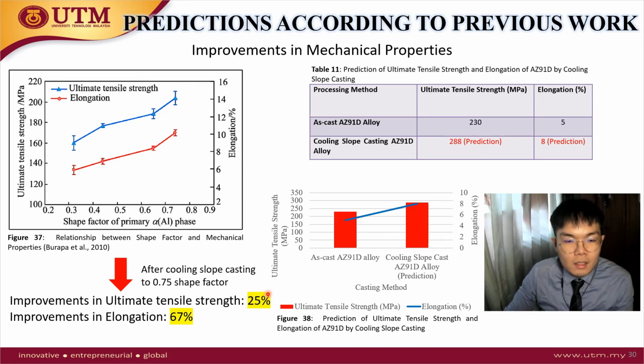By applying these improvements, we predict when we cooling slope cast AZ91D magnesium alloy to become 0.75 shape factor, we can obtain 288 megapascal of ultimate tensile strength and 8% of elongation. This is to compare between the conventionally cast AZ91D and the cooling slope cast AZ91D.